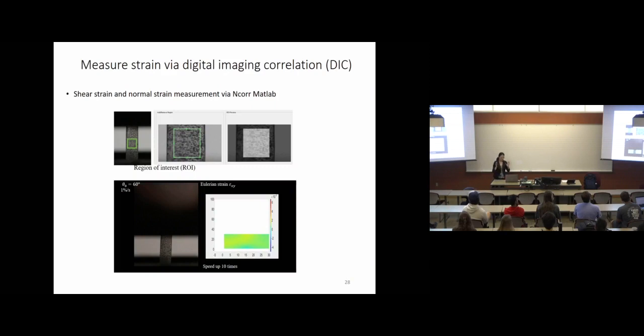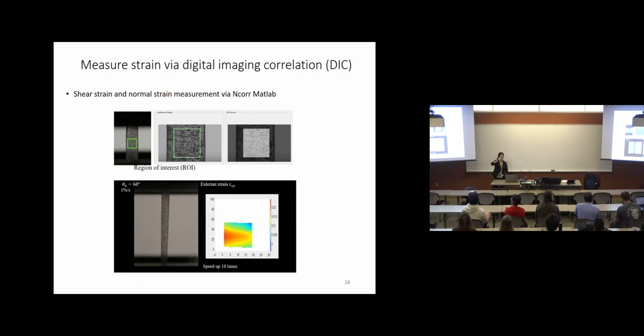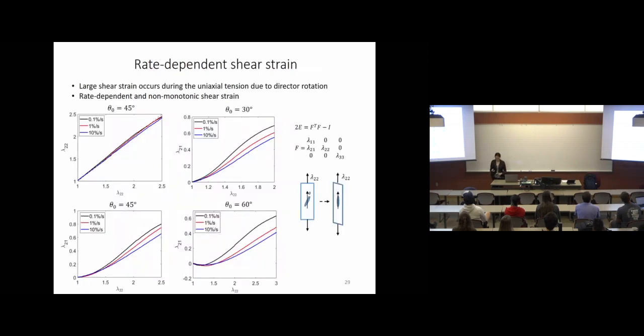Next, we also want to use the DIC method to capture the entire strain field in the material. In particular, the interesting thing is that even though you are doing only uniaxial loading, because the director is rotating, you expect a large shear strain in the material. That's why you see that initially the shape is rectangular, but after deformation it becomes a parallelogram. That's because of the large shear strain due to the director rotation. I'm further summarizing our result here.